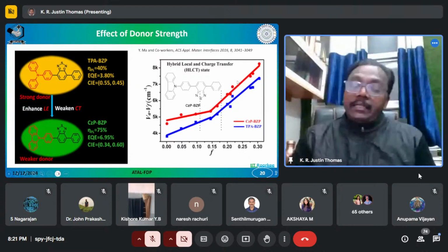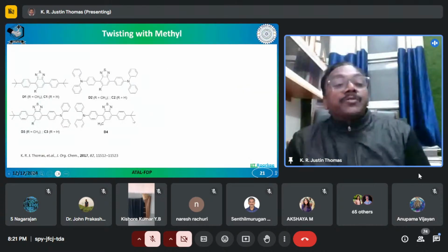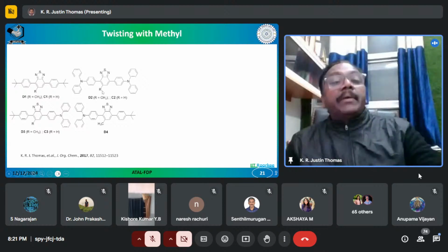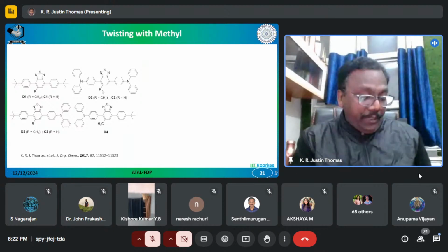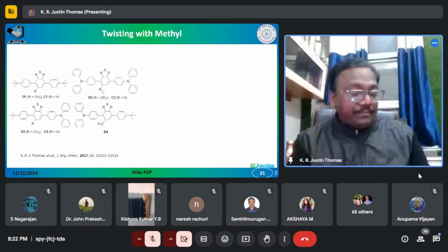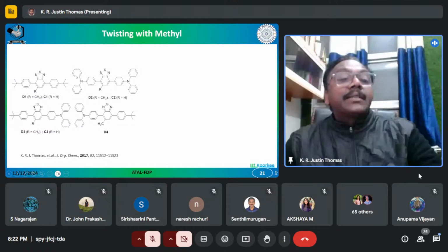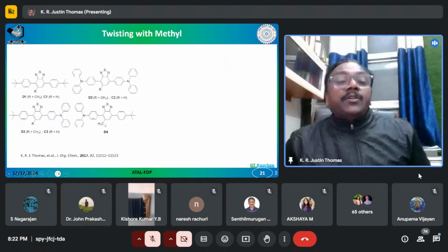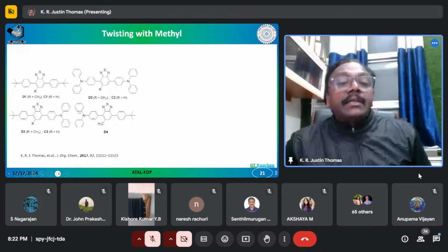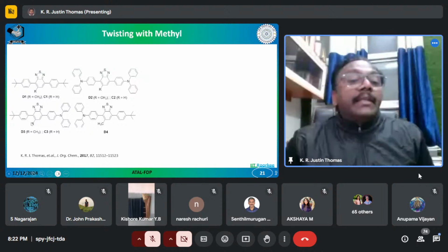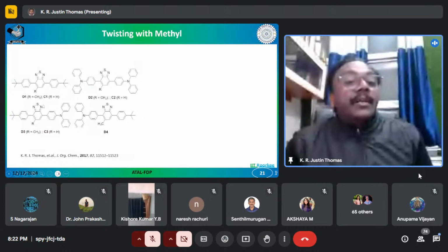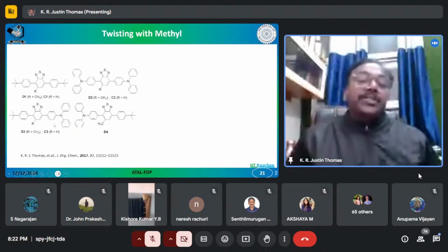Okay, and we have also found in 2017 that if you are using benzothiazole with a methyl group, because of this methyl group, there is a difference in the charge transfer characteristics of this molecule. So when the methyl group is tilting the donor unit, the charge transfer interaction is reduced. And if you look at all these molecules, you will come to understand that in this case, the methyl group is on the phenyl side, that is a dummy group. And then the triphenylamine donor is having a stronger interaction with this acceptor. So there will be an effective charge transfer.